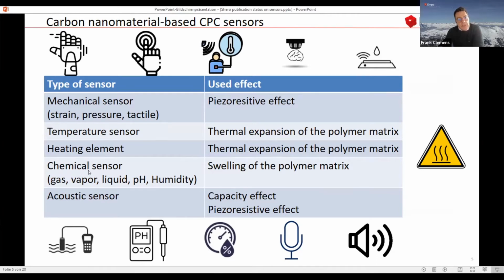And the other thing we can do is look at chemical sensors, which rely on a swelling of the polymer. And by this, we also get a larger difference, because the particles will not go closer together, they will go away from each other when we have the swelling effect. So the particle distance will get larger, as we have for the heating effect, but due to the swelling. And another point is that you can also make acoustic sensors. Already in the 1920s of the last century, for example, they made microphones based on these conductive composite materials based on carbon.